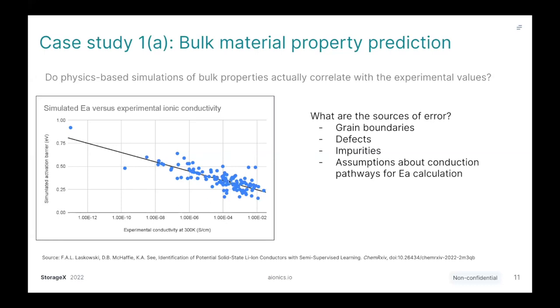And you can see that, hey, it's actually pretty good, right? And so what this means is if you take a new material and you estimate the diffusion barrier with, in this case, not DFT, but what's called the bond valence method, which is one level of simplicity above DFT, but you can think of it as in that same vein. If you run this experiment computationally and you see a low activation barrier, and then you take this material into the lab and try to make it and test the conductivity, well, there's a pretty good correlation. So things that show low activation barriers tend to be good conductors experimentally. That suggests that there might be some universality here.